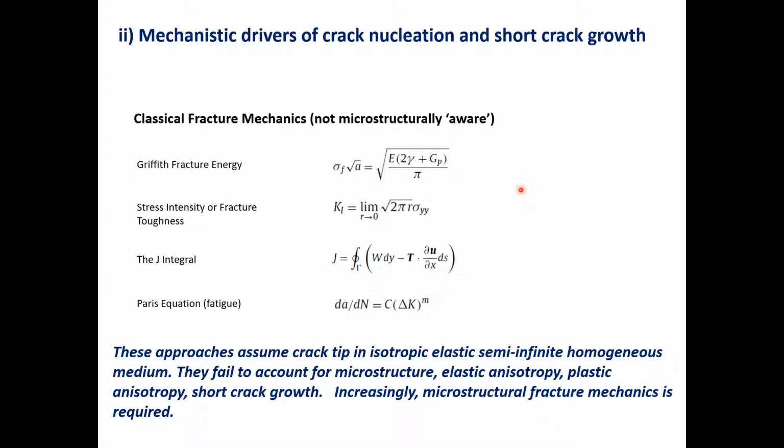You've got a homogeneous medium, and the crack is growing in an infinite medium where boundaries are infinitely far removed from the crack. So a range of limitations, and in addition to which neither of them explicitly recognise a microstructure as such. So as a crack approaches a grain boundary, for example, it's difficult to see how these approaches could be generalised to incorporate